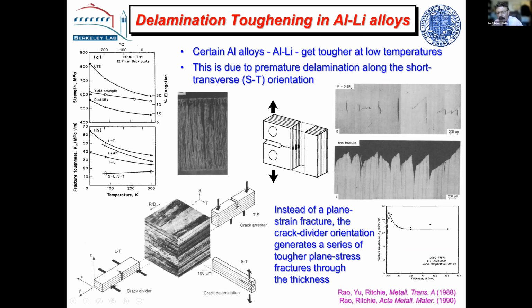Now, you've all seen this plot of the toughness versus the thickness. Plane stress is very high, and then it drops to plane strain. Well, by having these materials delaminate into these little tiny, they're not quite plane stress, they're non-plane strain fractures, you get a series of toughnesses up here rather than one segment down in the plane strain region. It's a fascinating sort of phenomenon, a little different, that crack divider, you generate a series of tougher plane stress regions rather than a single plane strain region.